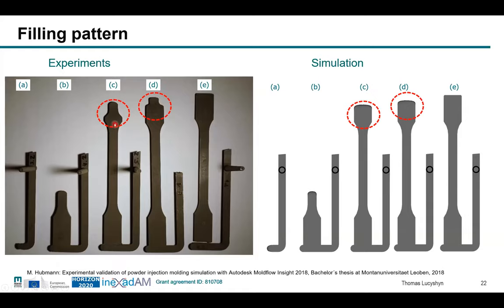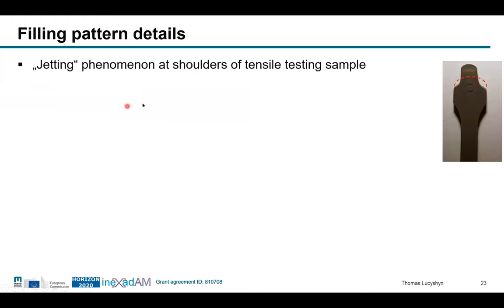The real behavior is that the material has a tendency to shoot forward and then afterwards it fills to the sides. But in the simulation, this cannot be considered, obviously. The simulation is not capable of doing this. So it fills like a conventional thermoplastic melt. If you had a thermoplastic melt like polypropylene, you would not see this phenomenon. This is really very specific for these powder injection feedstocks. So for normal materials, it would be fine, but for this specific material, there are still problems. This jetting phenomenon is not yet really